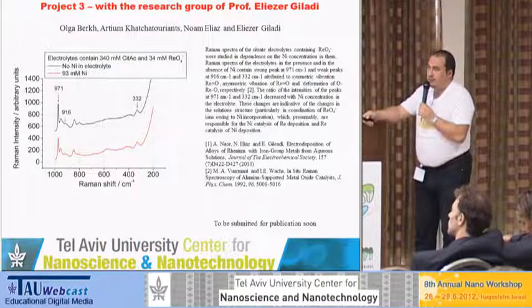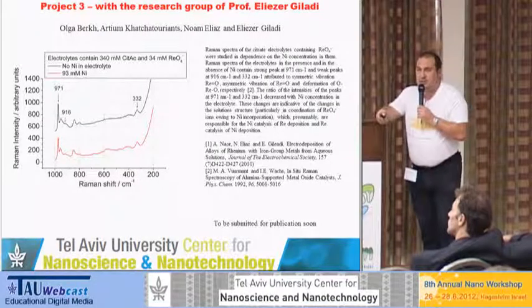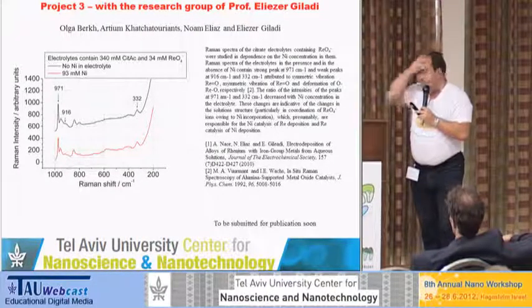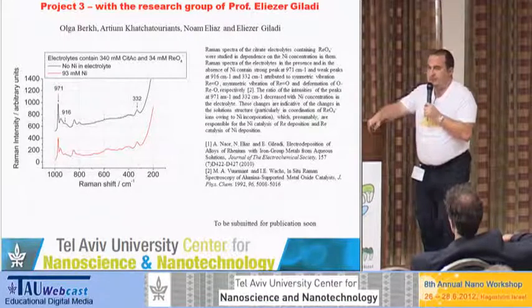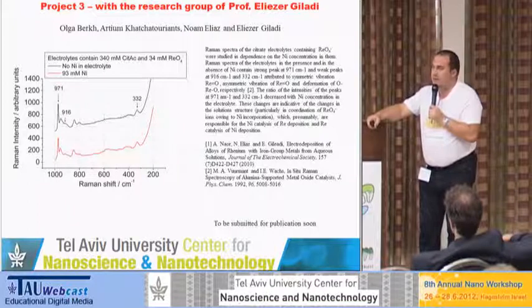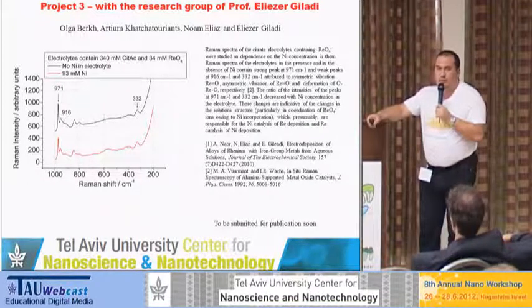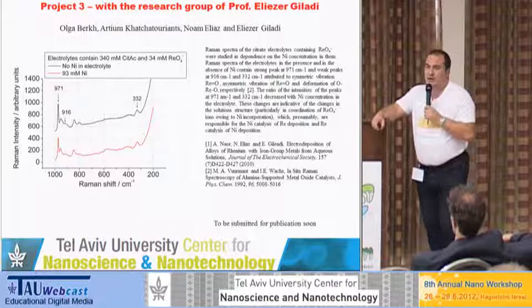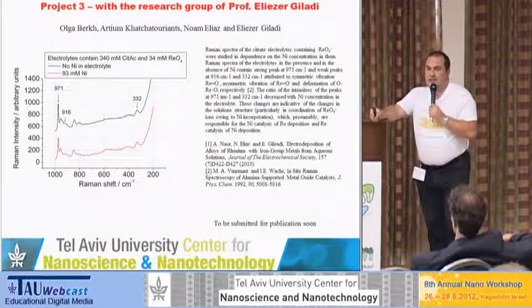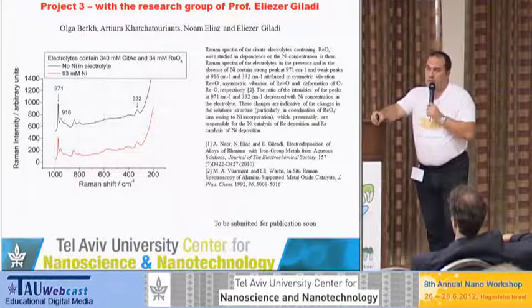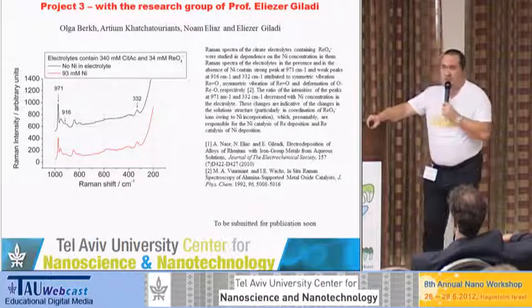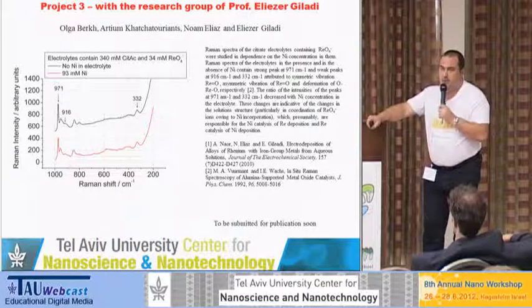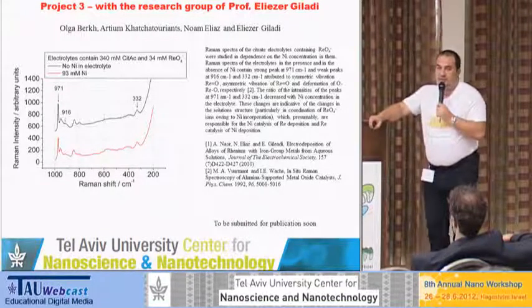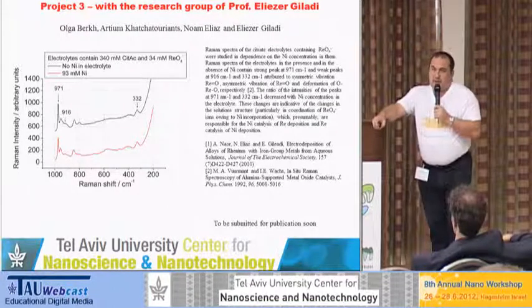And it is known that if, for example, in electrolytic solution only nickel is present without rhenium, or vice versa, then the coating efficiency and the electrolytic efficiency is quite poor. But if one adds some nickel concentration to the rhenium solution or vice versa, they act as a catalyst to each other, and the efficiency of the coating increases dramatically. So certainly there is some interaction between nickel and rhenium in this solution, and it is of interest to understand this interaction.